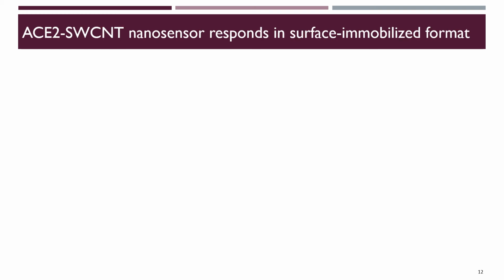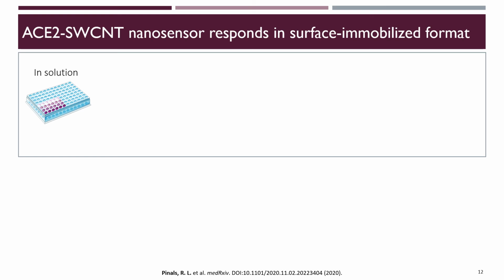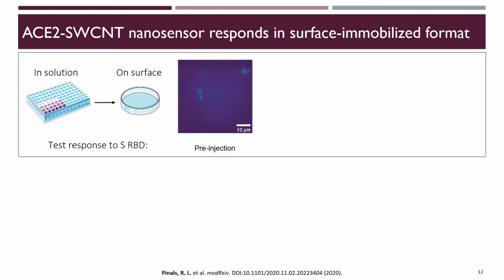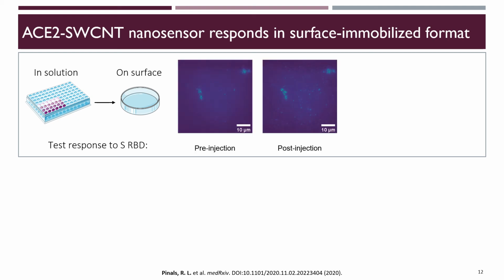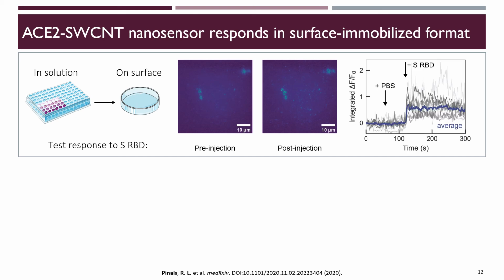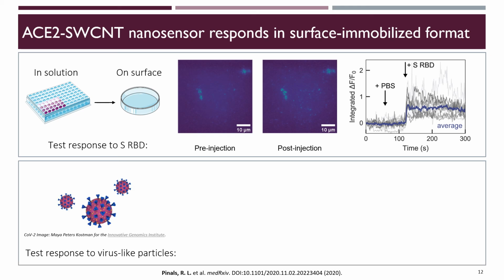Finally, I translated this nanosensor platform from an in-solution to surface immobilized format, as we see this as our next step in translating to point-of-care diagnostics. Excitingly, our nanosensors retain their response profile to the spike protein when immobilized on glass slides, as shown by these near-infrared images and traces, where the blue line averages over 12 regions of interest. Also importantly, the sensor response is rapid, maximizing within 5 seconds of analyte addition.